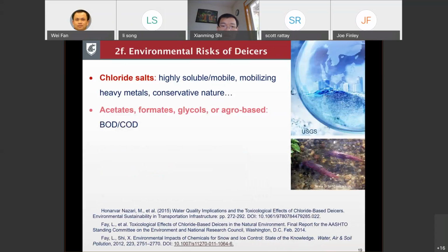Now, shifting gears to environmental risks, I already talked about chloride salts being highly soluble, mobile, and difficult to remove, or being conservative. Another piece of this is they also mobilize heavy metals out of the soil and the vegetation. So that's an environmental risk. Now, what about the non-chlorides? I already mentioned the potassium acetate, but there's also potassium formate, glycols, and other agricultural-based products. Their problem is not so much the long-term risk because they tend to degrade in the environment, but the short-term risk to water bodies is relatively high because they have a high oxygen demand, talking about biological or chemical oxygen demand.